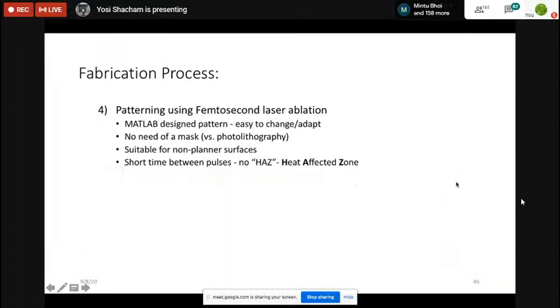Practically, let's focus on this part. If you have a nanosecond pulse, this is the laser pulse, you're heating the structure, and the heat, this red zone, is propagating. If you have femtosecond pulses, you are ablating the material, but the heat is not propagating, because the time is so short. The diffusion length of the heat, which is the square root of diffusivity times time, is so small, maybe a few angstroms, so there is no heating, only ablation. And because of that, we get a much cleaner cut and much nicer structures.